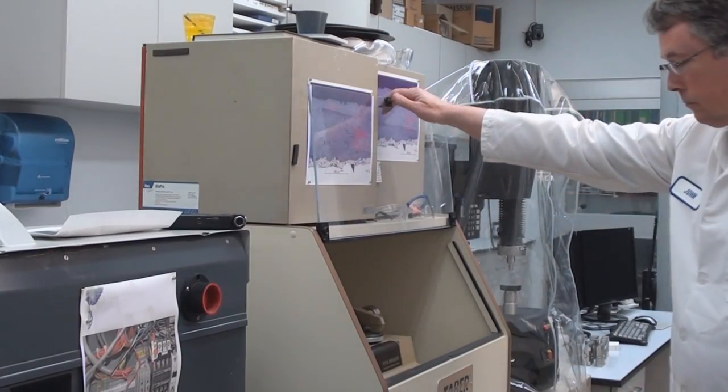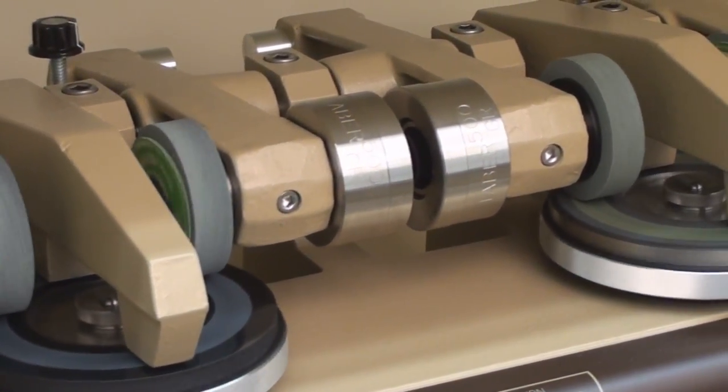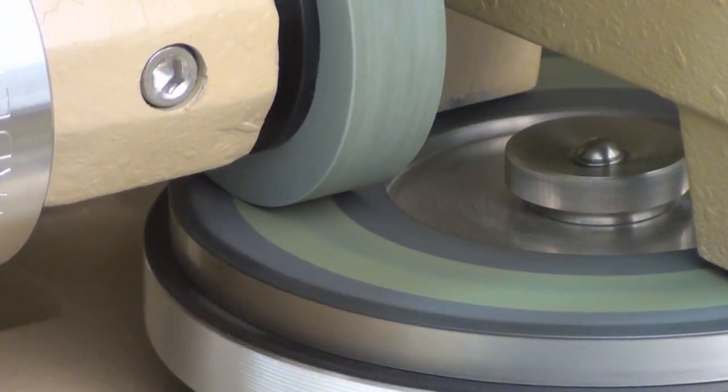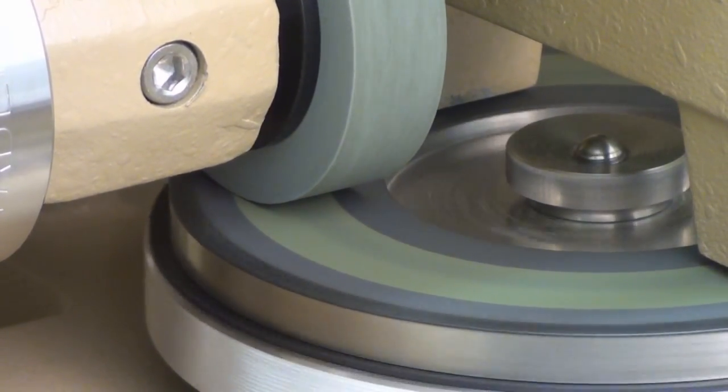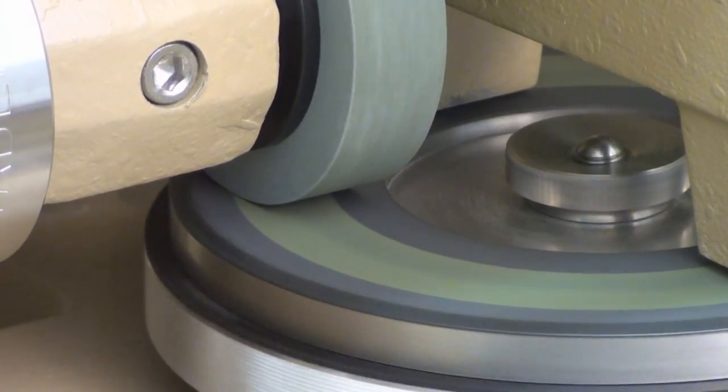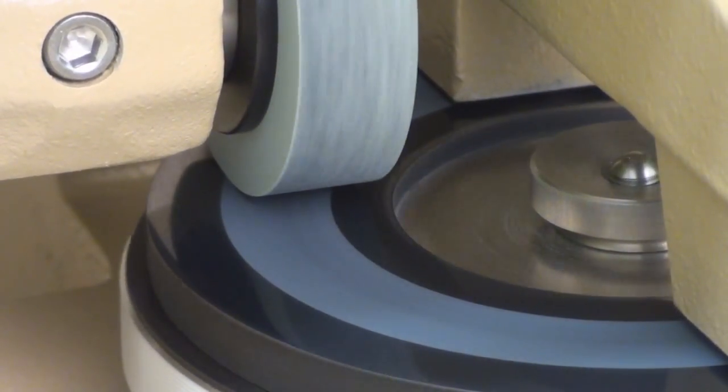The Taber abrasion test quantifies the ceramic coating's wear resistance to particles shedding on the surface. During this test, coated panels are rotated while in contact with a rotating wear surface made of silicon carbide. The panels are cleaned and weighed after a specific number of cycles and the data is compared to previous coatings. This may be useful for measuring scratch resistance, cleavage, and particle shedding of the coating.